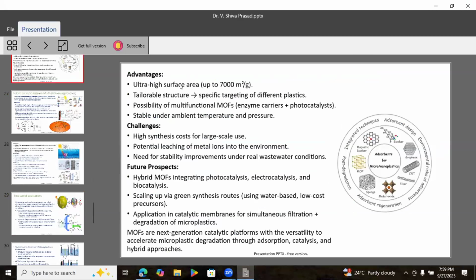Advantages in this system: ultra-high surface area, up to 7,000 square meters per gram, and tailorable structure for specific targeting of different plastics, and the possibility of multifunctional MOFs, enzyme carriers plus photocatalyst, stable under ambient temperature. Challenges: high synthesis cost for large-scale use, potential leaching of metal ions into the environment, and the need for stability improvements under real wastewater conditions. MOFs are next-generation catalytic platforms with the versatility to accelerate microplastic degradation through adsorption, catalysis, and hybrid approaches.